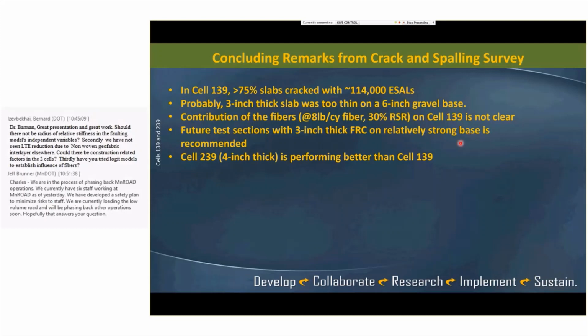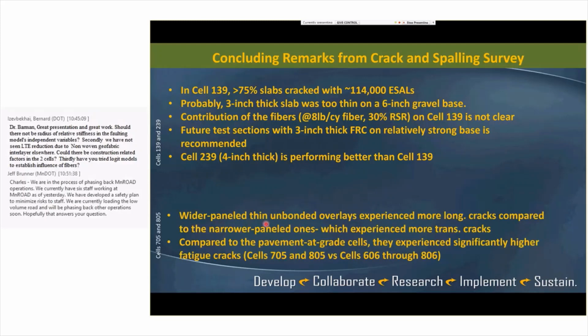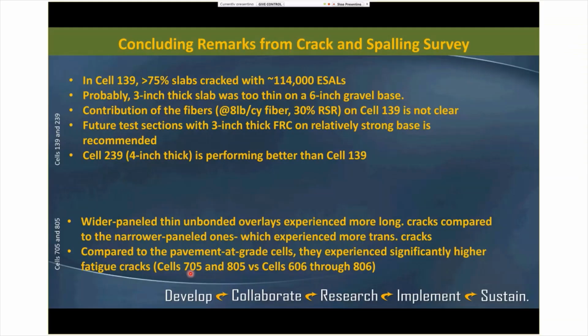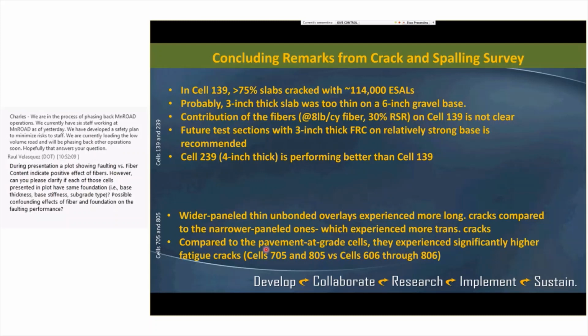Cell 239 performed better than 139. Wider panels in concrete overlays, thin unbonded overlays, experienced more longitudinal cracks compared to the narrower panel ones, which experienced more transverse cracks. Compared to the pavement on gravel, they experienced significantly higher fatigue cracks, like cells 705 and 805 have more cracks than cells 606 through 806, which were constructed on the gravel base, or a relatively strong base.